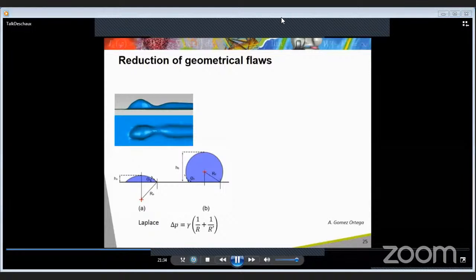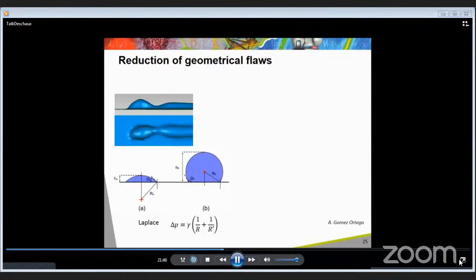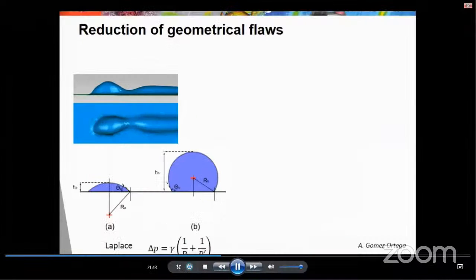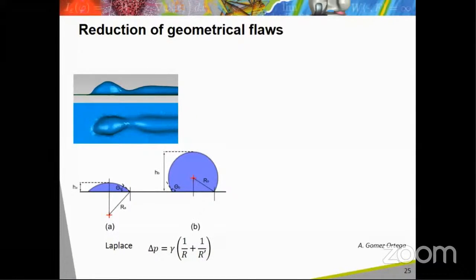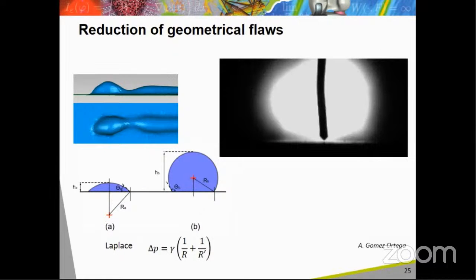On the opposite, when the contact angle is below 90 degrees, then an increase of the bead height produces an increase of the curvature radius, and so a decrease of the pressure in the liquid. This pressure decrease promotes the suction of the neighboring liquid having a lower curvature radius, leading to the formation of a narrow neck just after the beginning of the deposited bead. One can see on the video here the formation of this kind of flow.